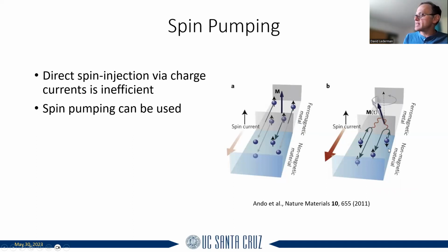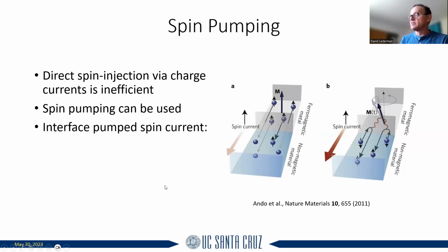And then if you have something with strong spin orbit coupling, as it turns out, the spin current can be quite strong. The spin pump current looks like this. It goes as M cross dM/dt. And again, dM/dt is involved because at the interface it acts like a dissipation force. It tries to stop the precession simply because at the interface there's no more magnetic material, right? So the exchange at the interface is different and you get dissipation of the precession.